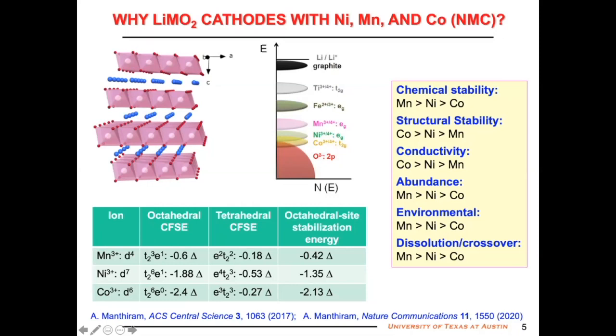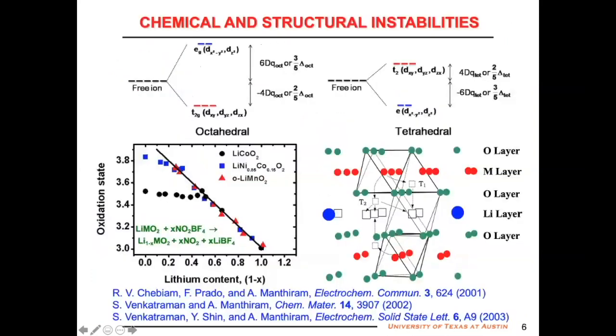So the first question is, why do we have three metal ions, NMC, rather than one metal ion for the cathode? The answer is each one of them has its own advantages and disadvantages. There are two major aspects. The first aspect is the relative position of these redox couples with respect to the top of the oxygen 2p band. Cobalt 3+/4+ overlaps with the top of the oxygen 2p band, so it has chemical instability.